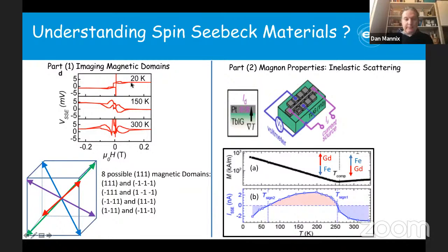So you can have a lot of magnetic domains in these structures. The second part of this talk is going to talk about another effect that is kind of interesting. First of all, if you look at the voltage or the current that's generated by the spin-Seebeck effect as a function of temperature, there's a sign change at higher temperature, and that's maybe easy to understand due to the switchover of the sublattices, the iron and gadolinium sublattices, at T compensation.